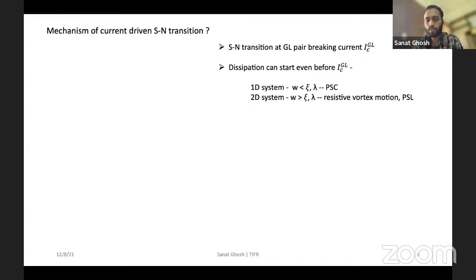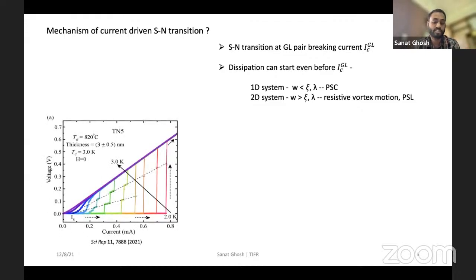But when you have a reduced dimension, for example in a 1D system, when the width of the nanowire is less than the superconducting coherence length and the magnetic penetration depth, then the dissipation can also occur in terms of phase slip centers, where along the length of the nanowire, some part momentarily becomes normal and starts dissipating. A similar situation occurs in a 2D system also, where the width of the nanowire is larger than lambda and xi, where resistive vortex motion can happen, and the 2D analog of the phase slip center, which is the phase slip line, can start dissipating in your system.